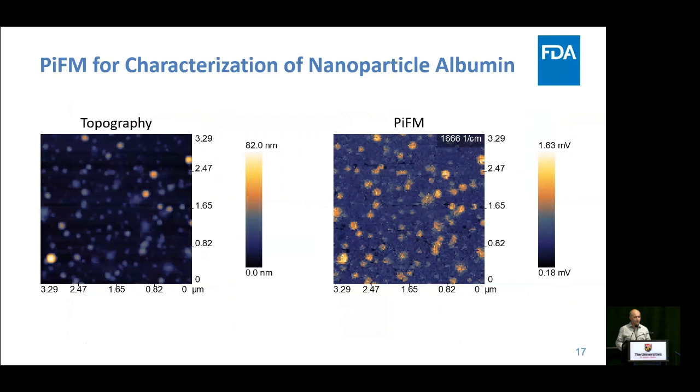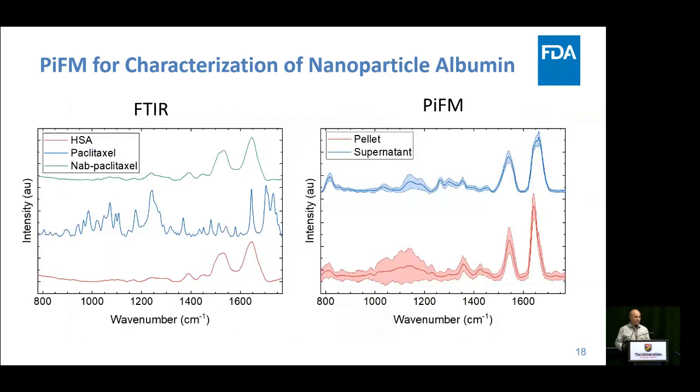And now what's really interesting is we did the centrifugation of the actual product. So let's look at the FTIR spectra quickly. The HSA again shows amide 2 and amide 1. For the paclitaxel, the two peaks at 1700 and 1730 are in crystalline paclitaxel; they don't show up in amorphous paclitaxel. It's also very interesting because now we can not only detect the paclitaxel inside the nanoparticle, but also confirm that it's non-crystalline, amorphous paclitaxel, in the FTIR spectrum from the nanoparticle albumin paclitaxel drug.